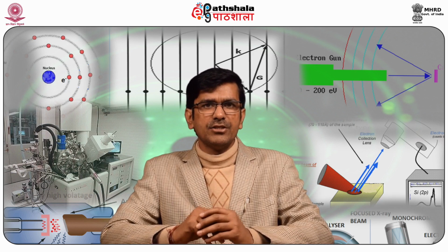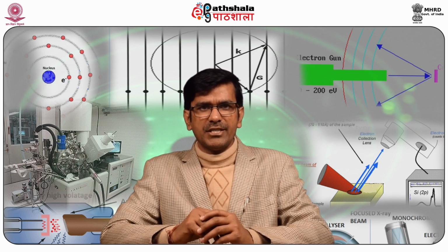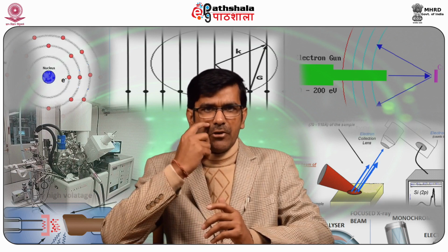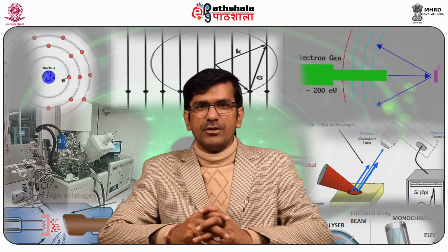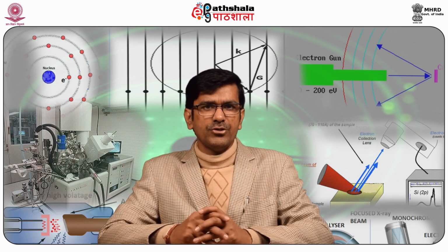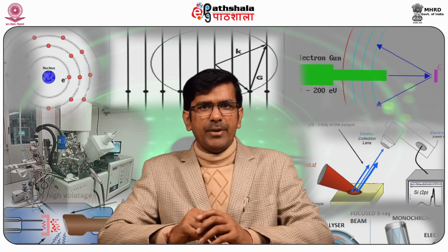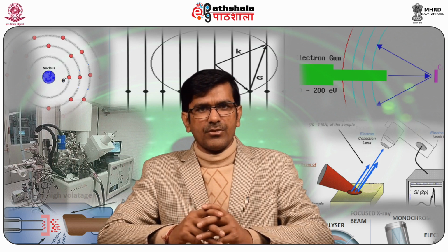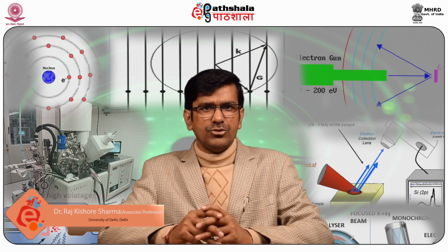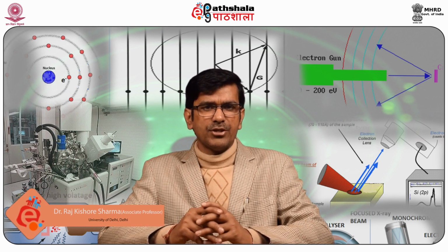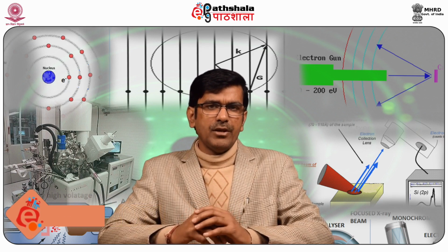Last but not least, we will discuss the disadvantages of SIMS. There is a lot of mass interference. The yield of secondary ions varies by more than 6 orders of magnitude over the periodic table. The yield of secondary ions depends on the matrix. In order to quantify data, numerous secondary standards are required. To obtain the best depth resolution, a flat surface of the sample is required.